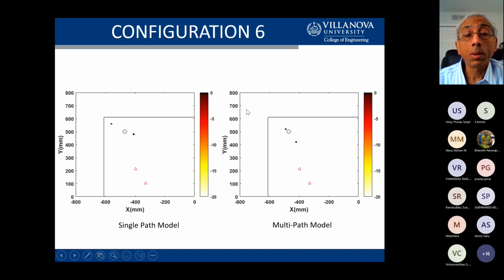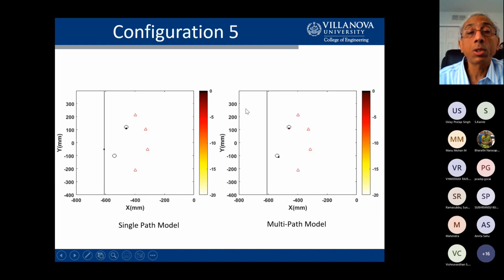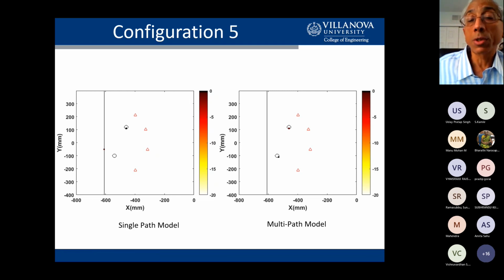I think I jumped too fast. Just one more slide here. This time we've got 2 defects, 2 circles here, and you want to locate where they are. Single path model, you locate one of them, but not the other. You notice that the prediction for the second one is over there. That's bad. On the other hand, if you use multi-path, you can spot where the 2 defects are fairly precisely. So it's a very effective method using sparse reconstruction in conjunction with multipath modeling.